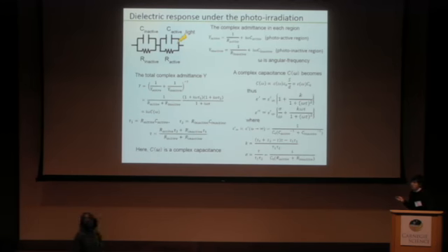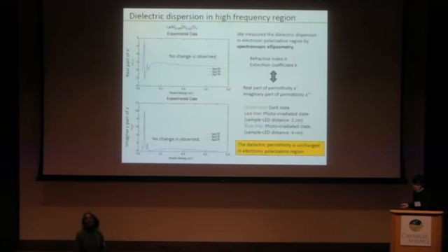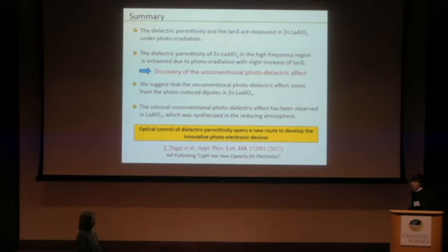But you have always some oxygen vacancies, and then you can have some localized level in band gap. I remind you, try to measure permittivity on samples with different thickness, and then you will have a direct proof whether it is defect or real effect. Okay. Defect, number of defects.